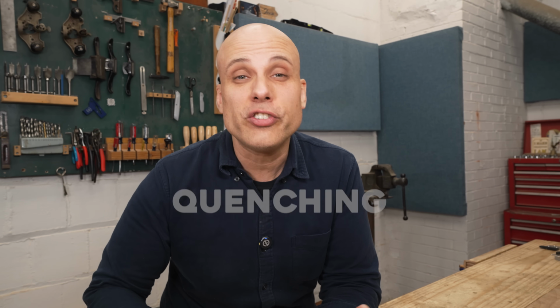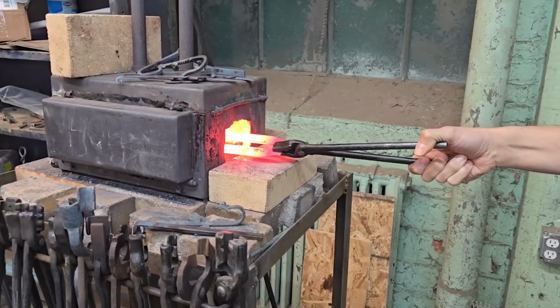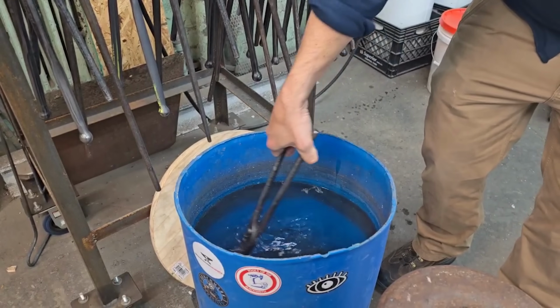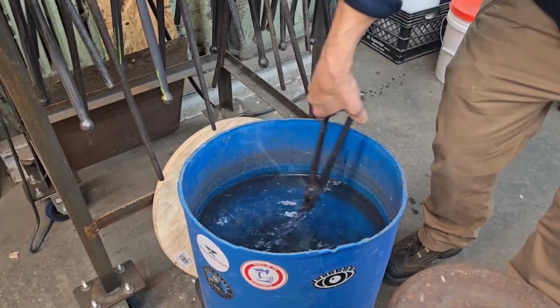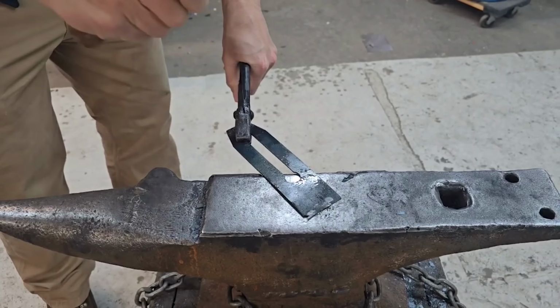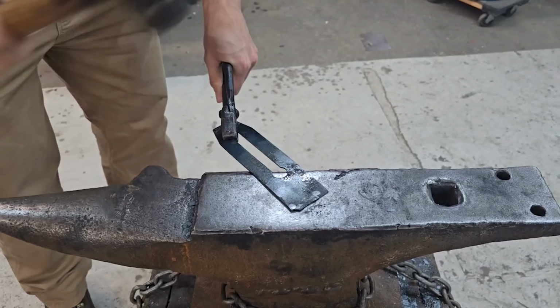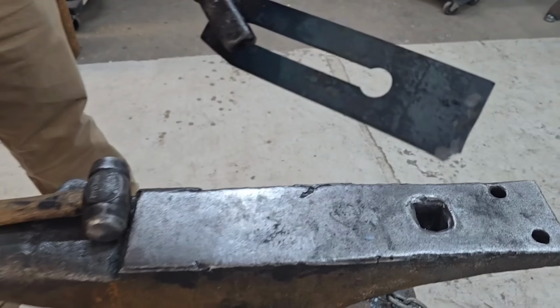Here's why. Basic tool steel is just iron plus carbon, and if it has the right amount of carbon, you can heat it up to a high temperature and then cool it down really fast. That's called quenching. And after quenching, the iron and the carbon are combined together in this really special way that makes the steel super hard, and it'll hold an edge much longer than a plain unhardened steel. The only problem with hardening is that it also makes the steel really brittle, so it'll crack or chip really easily.